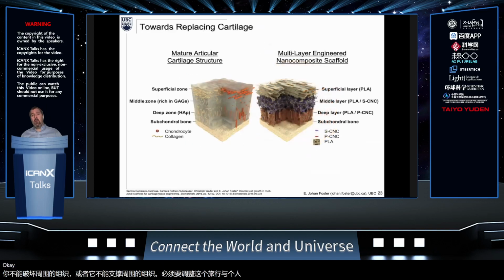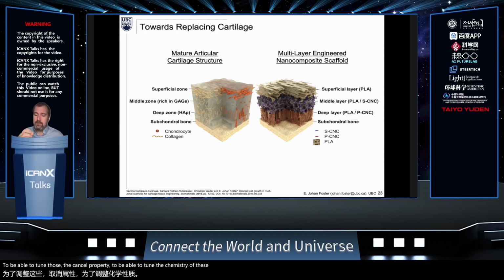Okay, so what do we want to do? Well, we want to utilize our cellulose nanocrystals to be able to tune those mechanical properties, to be able to tune the chemistry of this system, to make something that we can tune to an individual. So a 3-layer system where we mimic the cartilage that's in nature. A superficial layer, a middle layer, and a deep layer, again with that same sort of alignment. And we imbibe this with the chemistry by tuning the chemistry on the surface of the cellulose nanocrystals.